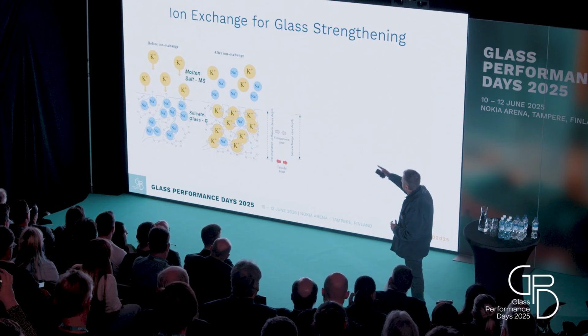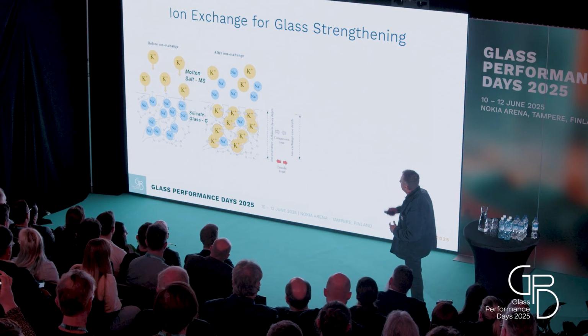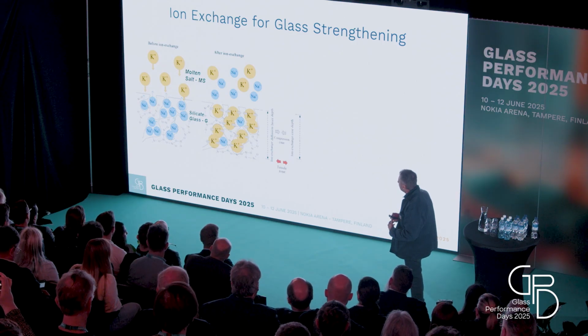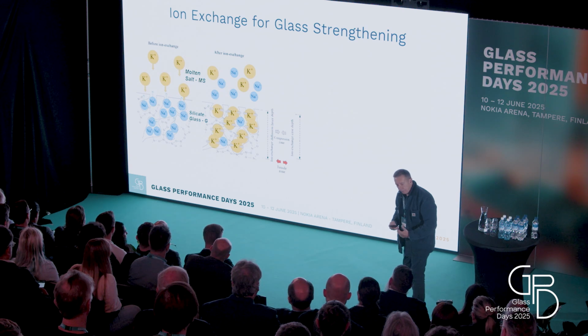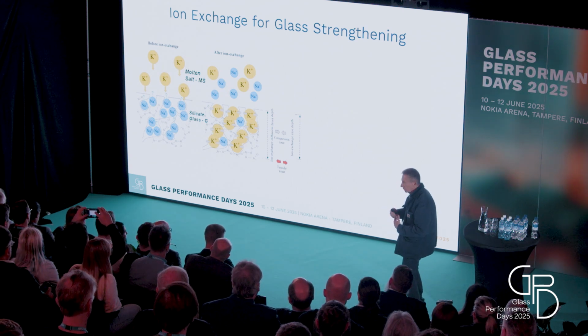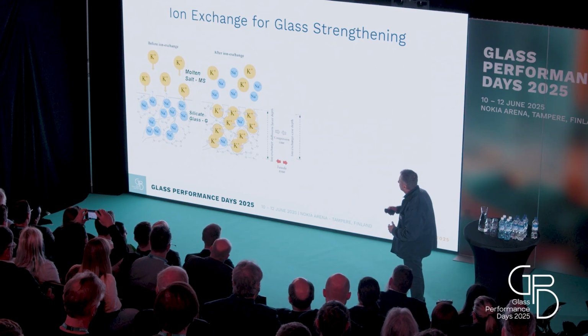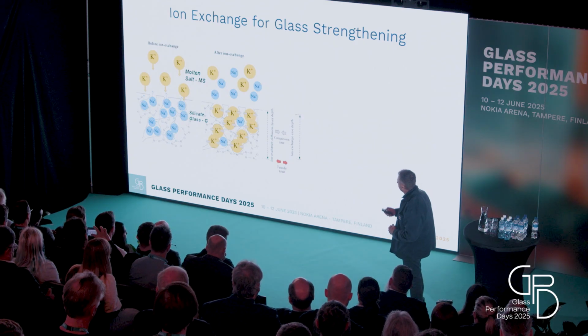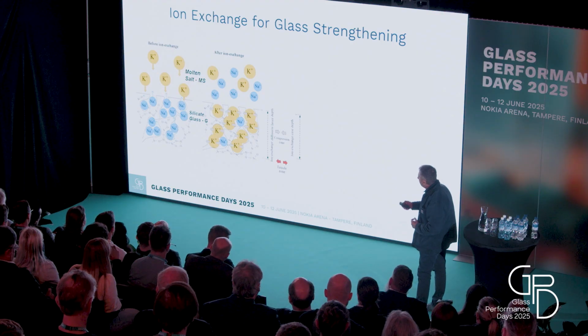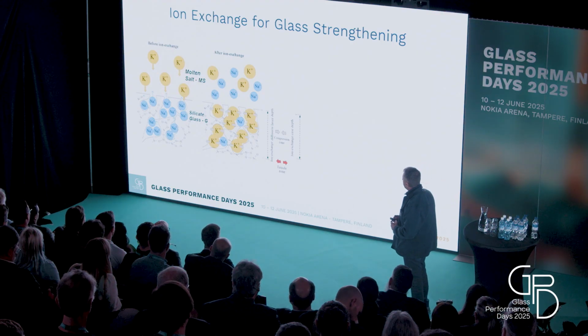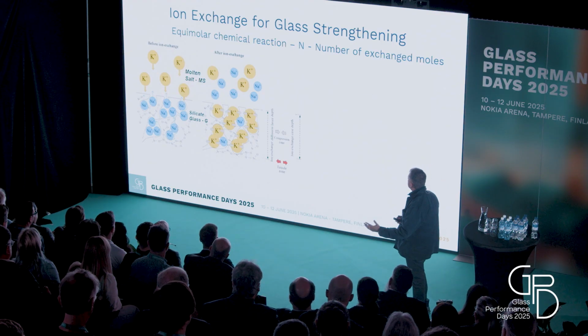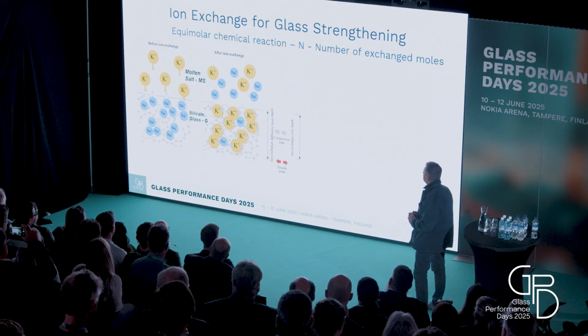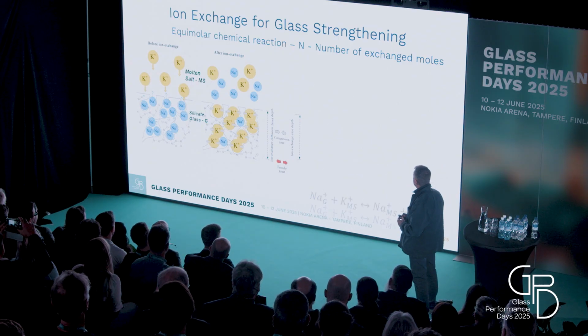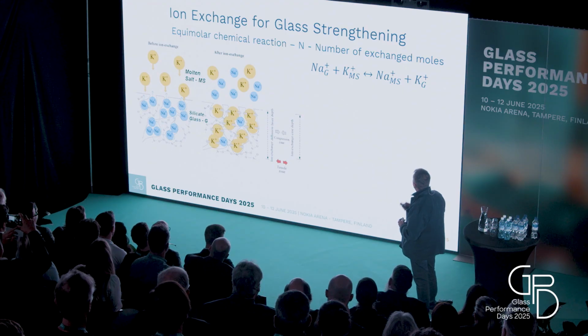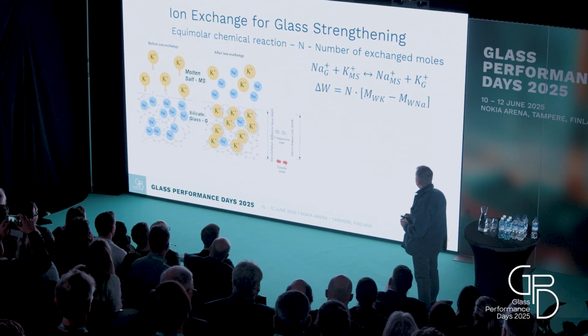And then the molar volume of potassium is larger, and that's why you have strain at the surface, which is uncompensated because the process is done below the glass transition temperature. This and the internal part create the constraints that generate the compression at the surface, balanced by a tensile zone in the inner one. So this is an equimolar chemical reaction characterized by the number of exchanged moles. This is how we can write down the chemical reaction.